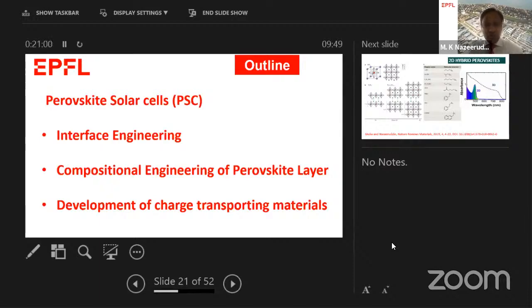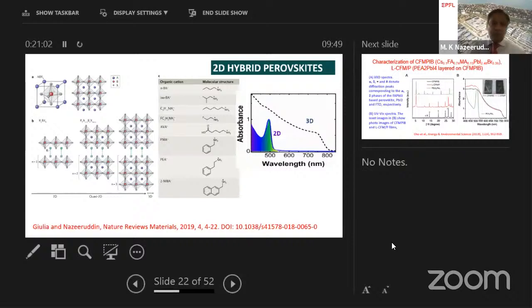The next slide shows you the difference between the 3-dimensional perovskite and 2-dimensional perovskite. On the top left side, what you are seeing is a 3-dimensional perovskite. When you mix lead iodide with the corresponding organic cation, it self-assembles into a 3-dimensional framework, and it's called a 3-dimensional perovskite.